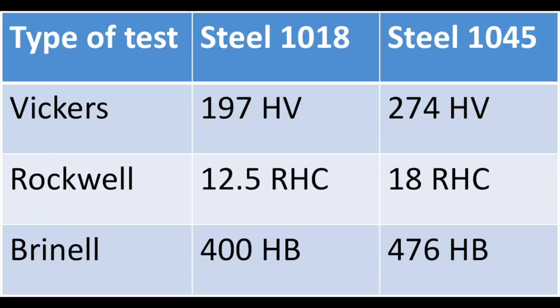This is the results table for the hardness test for both steels. And this could be expected. The 1045 steel, as it has more carbon, should be harder, and the results show that it is harder using the 3 methods: Vickers, Rockwell, and Brinell. This was a result exactly as expected.